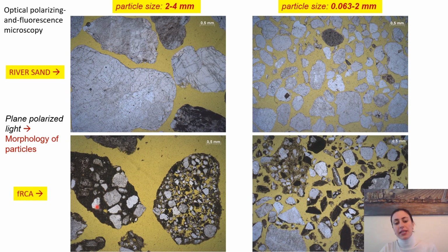Cement paste in recycled sand is actually layered around these primary aggregates, the sand particles in concrete. Then you can see two particles, and they have absolutely different qualities. One is very dense, let's say with the cement paste around, and another one has a very porous cement paste, and consequently it probably comes from low quality concrete.